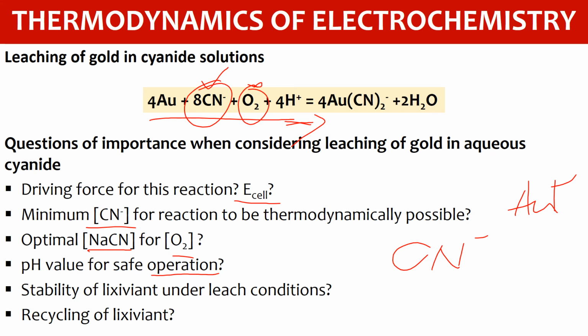For example, if you have lots of concentration of copper in the system, because copper is a cyanide consumer, you need to understand to what extent I should recycle my lixiviant. Because if the copper is in high concentration, it will also begin to adsorb. It also begins to follow even the elution and electrowinning circuit, and you need to avoid that.